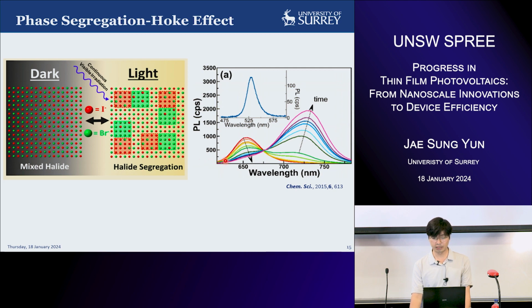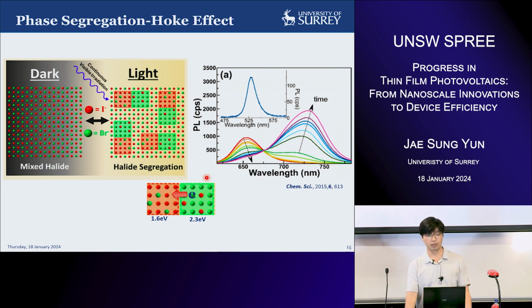So ultimately what happens is that if you measure PL, this is the original PL signal, you can see that as you continuously illuminate light, you evolve two peaks of the PL. So there is the iodine peak, iodine rich peak, and there is a bromide rich peak. So you will eventually have around 1.6 eV narrow band gap and wider band gap regions formed in your material, and there are going to be a carrier funneling.